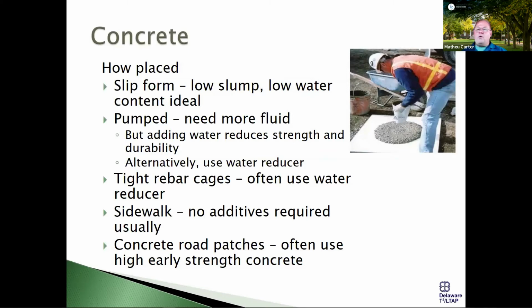We would cover all that with wet burlap and plastic and thermal blankets. We'd have to stop traffic in both directions because when we pulled the blankets off, the amount of steam took visibility to zero because there was so much heat in this concrete. So there you were using very specialized mixes that would give you a very early high strength without necessarily sacrificing durability.